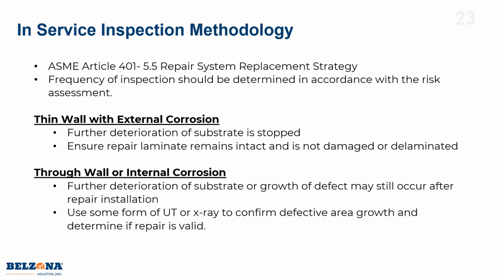So once you're in the field, you've got a good repair, good design, good installation. The in-service inspection methodology per ASME is that the frequency of inspection should be determined in accordance with the risk assessment. It has two sections, one for thin wall with external corrosion and one for through wall or internal corrosion. For thin wall with external corrosion, further deterioration of the substrate is stopped. The main inspection is just to ensure that the repair laminate remains intact and not delaminated. You go there, check on it, make sure there are no cracks, it hasn't debonded, a forklift hasn't hit it, stuff like that.